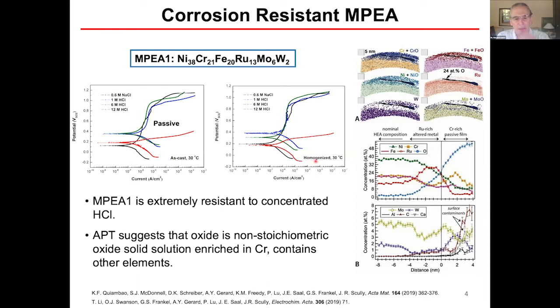So these are arc melted buttons that we have tested, again, either as cast or we hold it at a high temperature to make sure it's well homogenized. And you can see we're testing in a range of chloride concentration up to 12 molar HCl. So 12 molar HCl is what you get out of the bottle. And 6 molar HCl might represent the concentration that would exist in a local pit environment.